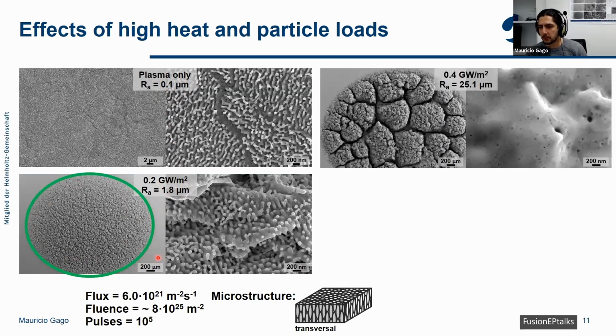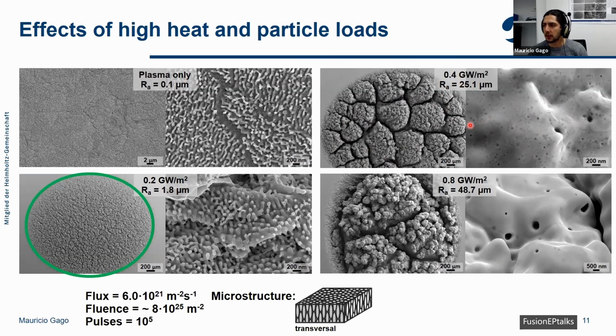Now the power density was increased. Everything else remained similar. And we can see already a very large crack network being formed and pores being formed in the surface. Another important fact to observe is that we don't see any more tungsten fuzz being formed here. And then getting closer to the power density expected for ELMs, we see that the cracks have become larger. There is a clear swelling in the surface of the sample, and the bubble formation increased. So the bubbles that are observed are actually larger than before. But also there is local melting that can be seen.